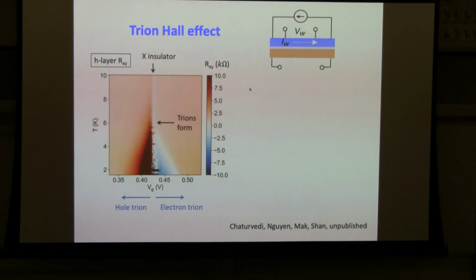Finally, I will just tell you a little bit about a quite surprising finding when you start measuring the Hall effect in this trion regime. Okay? So what we are doing here is still open circuit of the electron layer and measure the Hall effect of the whole layer. So this is the map of the whole layer Hall resistance as a function of temperature and the gate voltage, which tunes the electron and hole density imbalance.